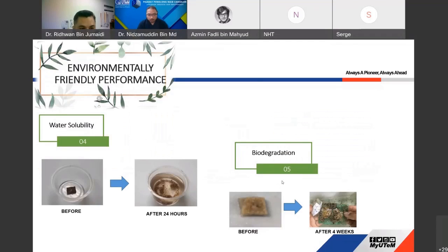For the durian fiber, this is the structure before. This one is more clear, this is before the water solubility test. After 24 hours of immersion in water, it can decompose like this. So it is safely decomposed after 24 hours, whereas other materials, even though they claim to be biodegradable, still take quite a long time to degrade.